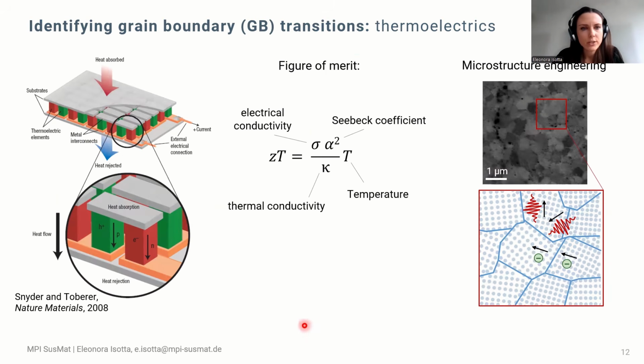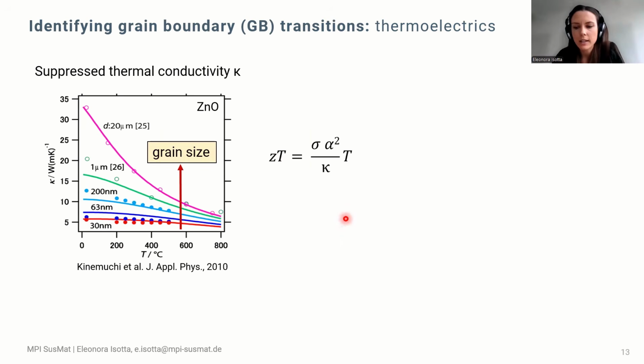When we think about thermoelectric materials, we typically want high performance materials with high electrical conductivity, high Seebeck coefficient, and at the same time low thermal conductivity. Among the different types of engineering done on thermoelectric materials, a powerful strategy is microstructure engineering. When we introduce a high amount of grain boundaries by varying the grain size, the typical expectation is that thermal conductivity will be suppressed with smaller grain sizes, and this is generally good for performance.